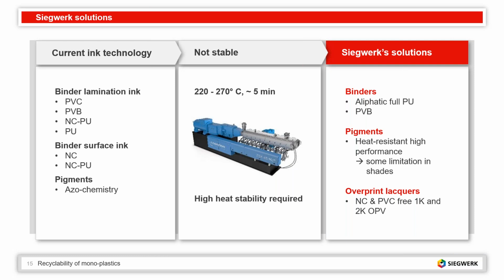Now, having said this, this setup or mix of inks today has some limitations, and you see in the middle the thermal stability, which I mentioned already, because re-extruding, recycling means melting up the polyolefins, polyethylene, polypropylene, to temperatures up to 270 degrees centigrade for several minutes. And in order to have an acceptable result, you need high heat stability.